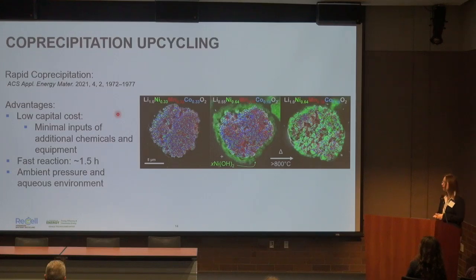So here I'm using a co-precipitation method. Co-precipitation is your main chemistry process for originally making these spherical, agglomerated particle cathode materials of lithium, nickel, cobalt, manganese, with a precursor of nickel, cobalt, manganese hydroxide. Basically, I'm coating our end-of-life cathode material with an NMC 111 composition with a high nickel-rich hydroxide shell.